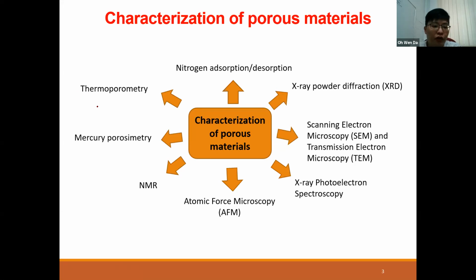These thermoporometry and mercury porosimetry methods are less likely used. They are seldom used compared to nitrogen adsorption desorption. So this method is more commonly used. The reason is that most of the time when you want to characterize a pore structure, the porosity of the activated carbon, it is usually in powdered or granular form. So if you are using granular or powdered form, the better approach to determine the surface area, pore volume, and pore densities would be nitrogen adsorption desorption, because this method is simpler and very easy to operate compared to thermoporometry and mercury porosimetry. That's why in all the papers that you have, you find most likely they use nitrogen adsorption desorption.